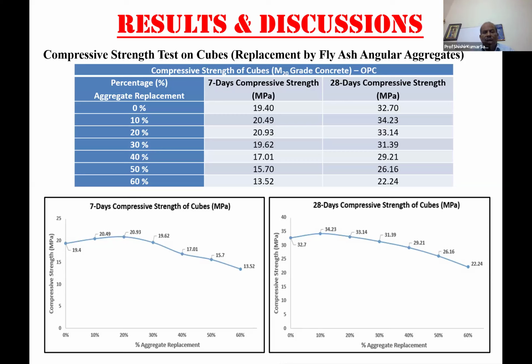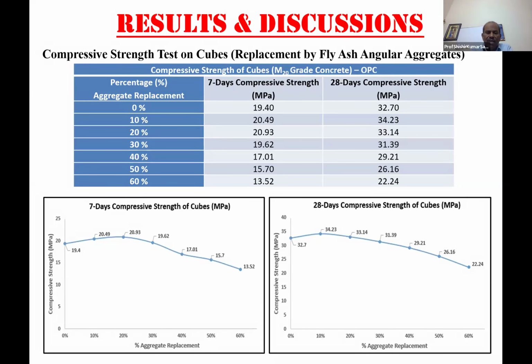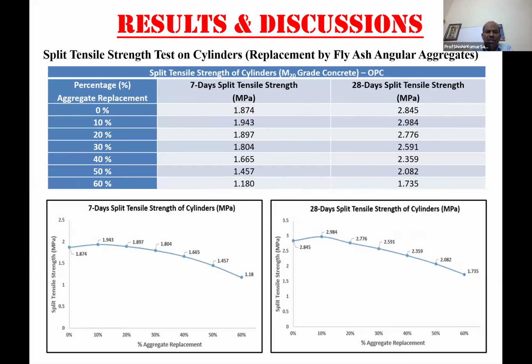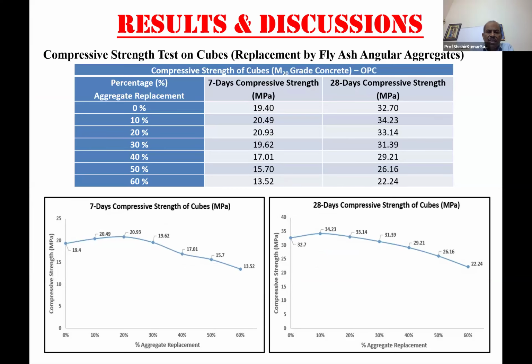So we have also used another method for manufacturing, two ways, and this is the compressive strength. This is the cube strength. So what is happening? Compressive strength at 28 days increases, then decreases, but is more than this. So something like 20% is optimum.